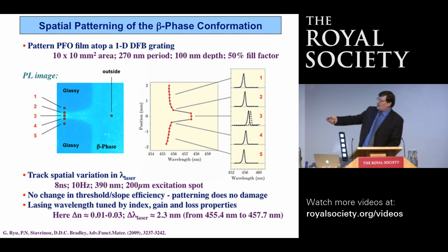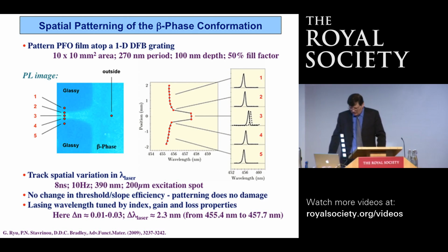One of the very nice things about these sorts of structures is that they're planar structures. We don't have to do any lithographic patterning or any electron beam writing or anything like that to generate the structures. There are no changes in the threshold or slope efficiency, so the patterning process is not doing any damage. And so it's actually very easy to think about making a range of structures where we could make use of this effect. And this is one of the areas that we've got work going on.